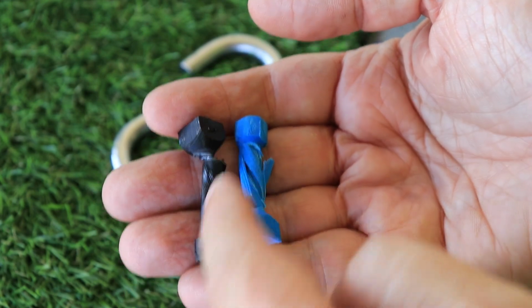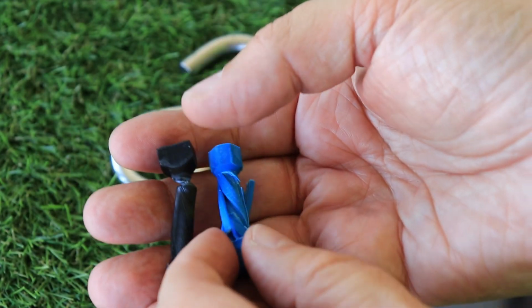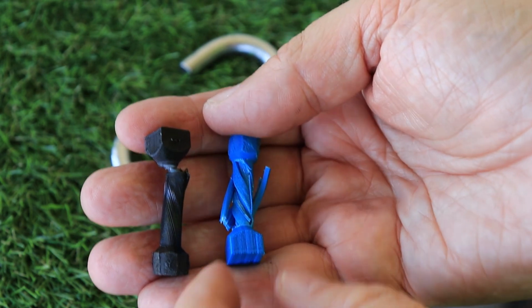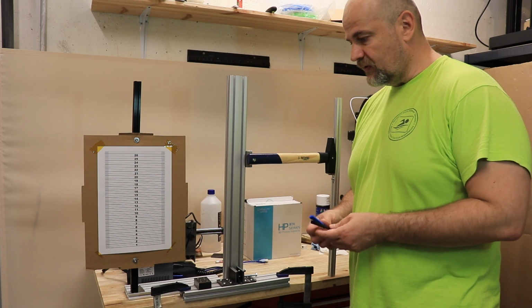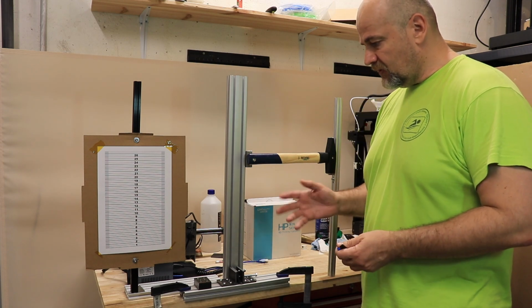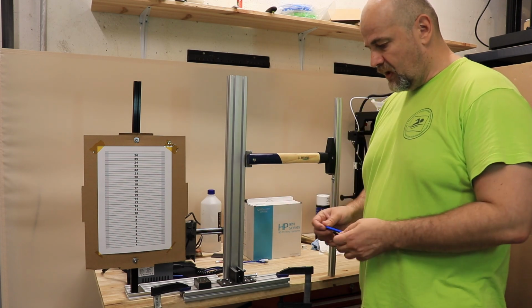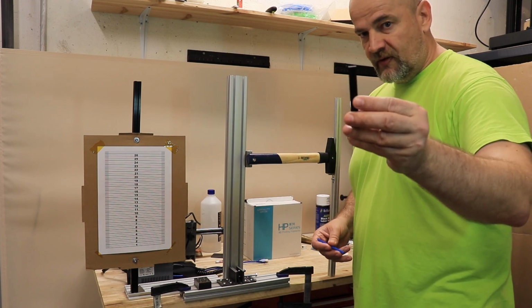Much nicer break was with the PLA Advanced, and this is typical sign of the weaker layer adhesion. And now let's see how brittle or tough are these materials. This is my equipment for IZOD impact test with a half kilogram hammer, and I'm starting with the PLA Advanced.